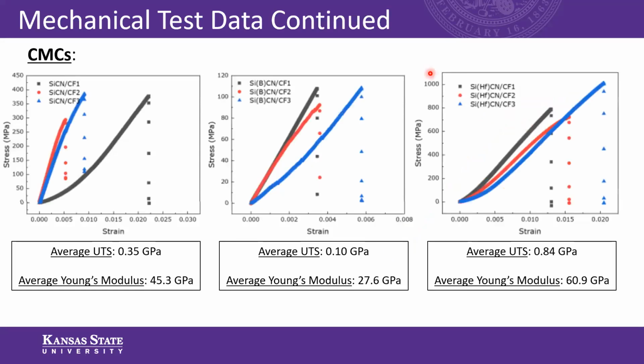Now for the CMCs, the results were also quite consistent throughout each sample. However, the results are as follows. For SiCN, the average ultimate tensile strength was 0.35 gigapascals, and the average Young's modulus was 45.3 gigapascals. For SiBCN, the average ultimate tensile strength was 0.1 gigapascal, and the average Young's modulus was 27.6 gigapascals. And for SiHFCN, the average ultimate tensile strength was 0.84 gigapascals, and the average Young's modulus was 60.9 gigapascals.